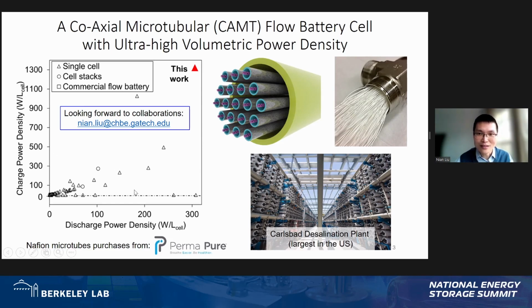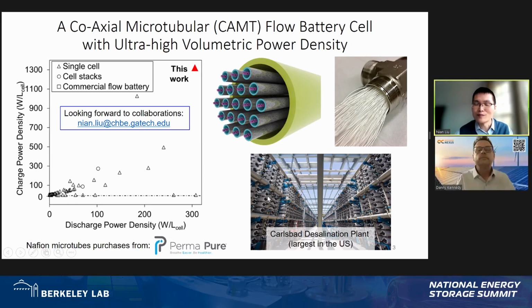So we are currently using the Nafion microtubes from a commercial source, and we think this technology is very scalable. You can make bundles of these microtubes together, and we have done this in the chemical separation. And in fact, the water desalination also chooses these kinds of tubular configurations rather than a planar one. So we think applying this to electrochemical flow batteries is a very promising and feasible way.